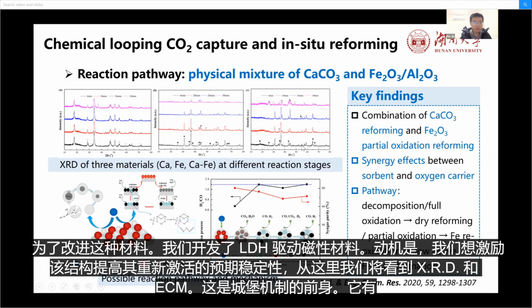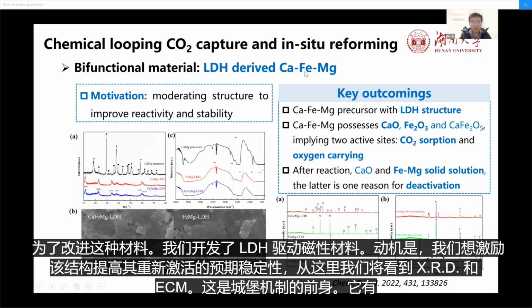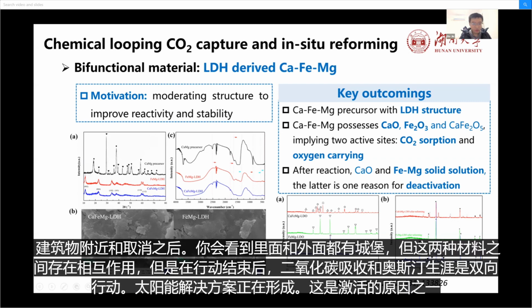In order to improve this material, we developed the LDH-derived calcium iron magnesium material. The motivation is that we want to modify the structure to improve its reactivity and stability. Here we'll see the XRD and the SEM. This is the precursor of calcium iron magnesium. It has the layered structure, and after the calcination, you'll see there's calcium oxide and iron oxide, but there's interaction between the two materials. It provides two active sites, the CO2 sorption and oxygen carrier. After reaction, there's the formation of solid solutions. This is one of the reasons for deactivation.